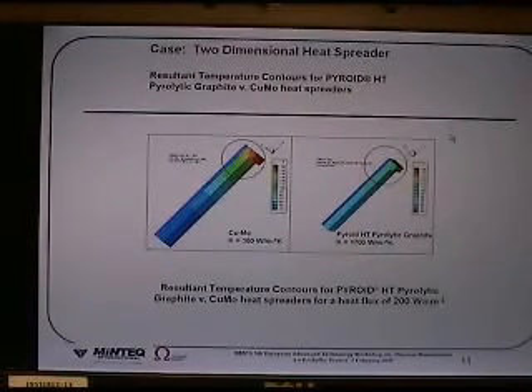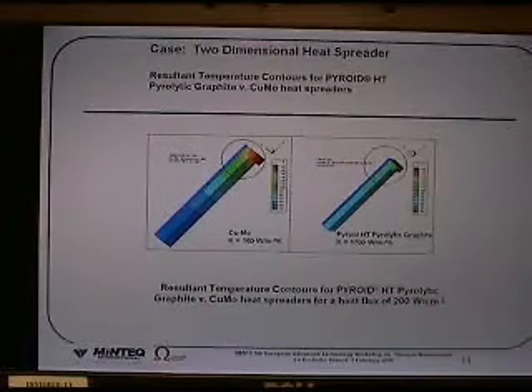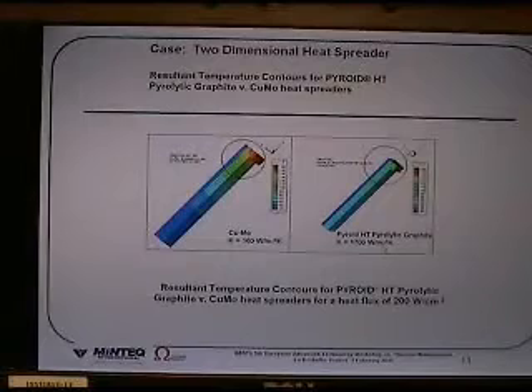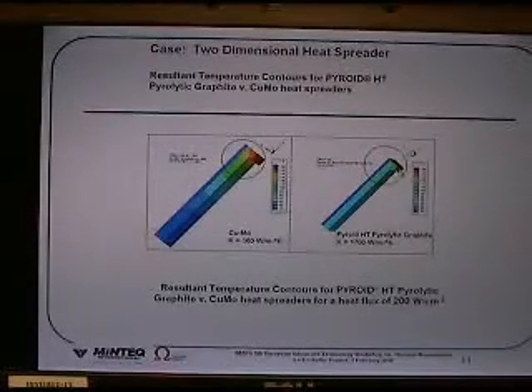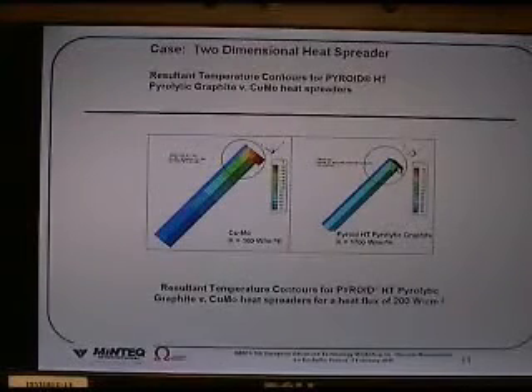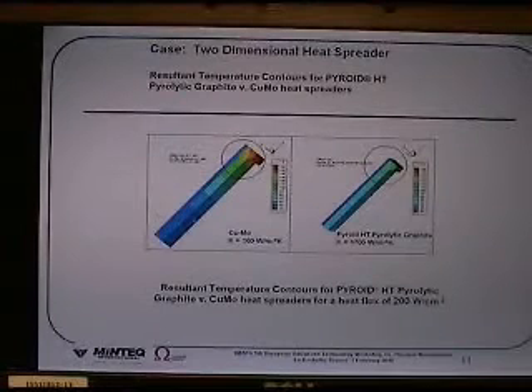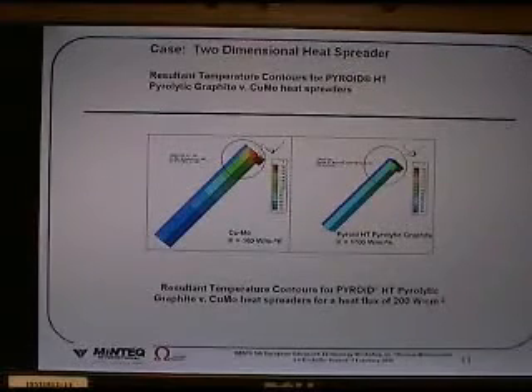The results of the thermal imaging are rather dramatic in that on this side we have a copper molybdenum, which is a 160 watt per meter K material, versus the Pyroid HT pyrolytic graphite at 1700 watts per meter K. And of course, as you notice, it's a very uniform and a very cool interface between the laser diode and our material, as opposed to the more traditional and hotter zone that you experience with either copper or copper molybdenum.